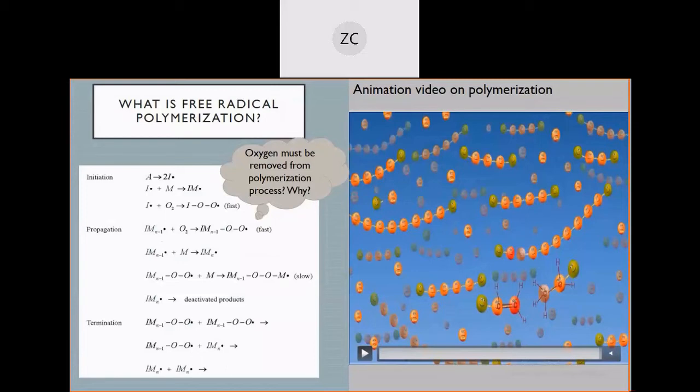With the presence of oxygen, the polymerization process is hard to control because oxygen will react with the initiator and monomer, which causes a wide range of molecular weight distribution of polymers. Secondly, the induction time to start the polymerization is disturbed by the presence of oxygen. It will take a longer time to start the reaction. Therefore, it is a must to remove the oxygen.